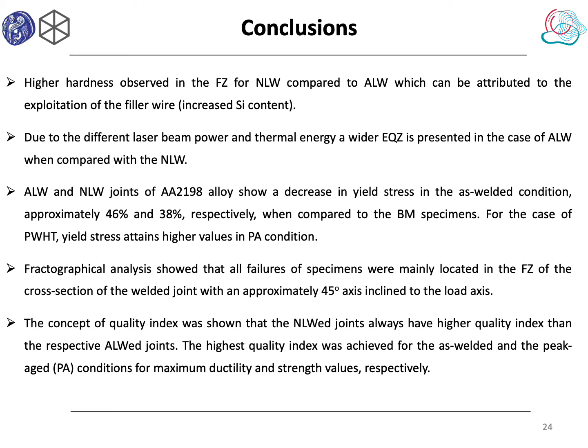Due to the different laser beam power and thermal energy, a wider equiaxed zone is present in the case of autogenous welds when compared with the non-autogenous. Autogenous and non-autogenous welds of 2198 alloy show a decrease in yield stress in the as-welded condition, approximately 46 and 38% respectively, when compared to the base material. For the case of the post-welding heat treatment, yield stress attains higher values in the peak aging condition.